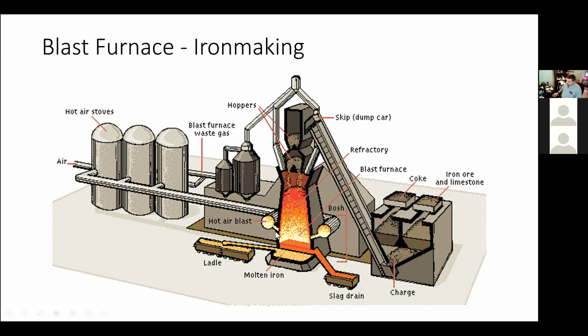But as we carry out the smelting of the iron ore in the blast furnace, we end up with gases that are produced. And these gases contain a lot of hydrogen and CO. And so what we do is we tend to collect those, and then we burn those to heat the air that we use to inject into the bottom of the furnace. And this air flows up through the furnace, reacting with the carbon and producing CO. And CO reduces the FeO to metallic iron. And by the time it reaches the bottom here, the metallic iron melts and it collects in the hearth here, and we actually tap off slag and molten iron separately to other vessels that take it to other parts of the plant.